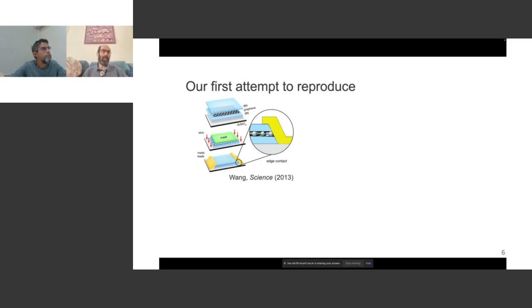technology that allowed the work by Andre Geim's group on graphene initially. But the technology for making single layers of graphene has largely stayed there in that same situation. I'll mention something else at the end, but the technology for making a really clean sample of graphene has evolved. And it turns out that now graphene can be sandwiched between insulating layers, so it's protected from its environment, and then contacts can be made to the edge of the graphene so that you can do electrical measurements on it.